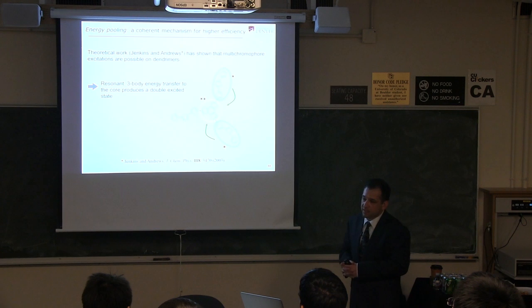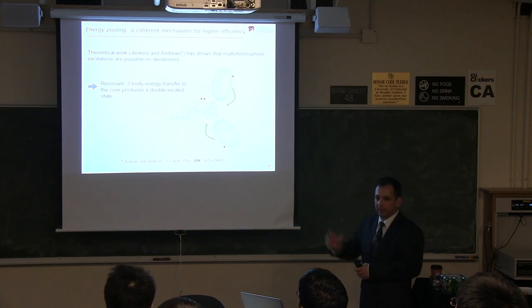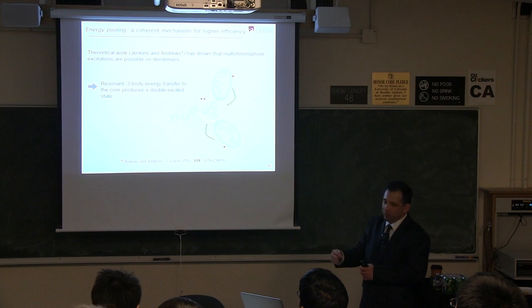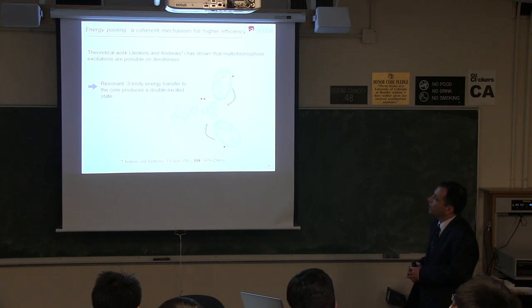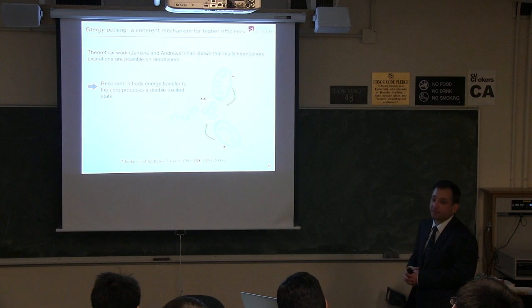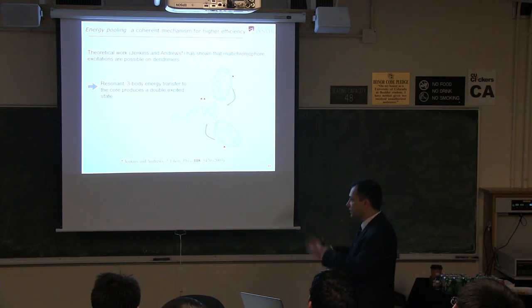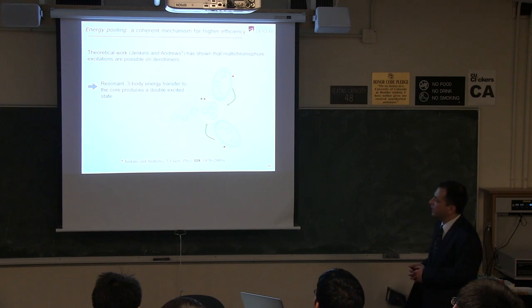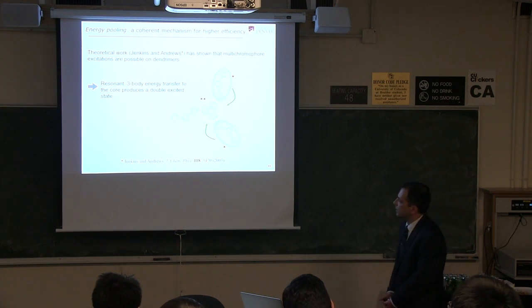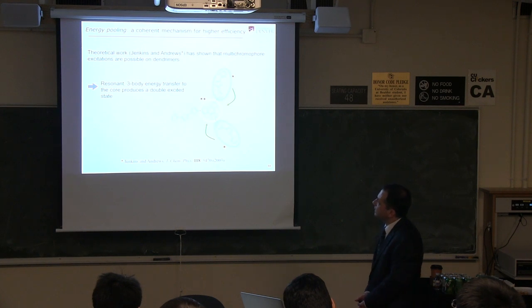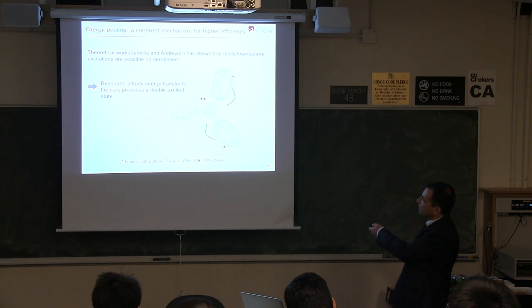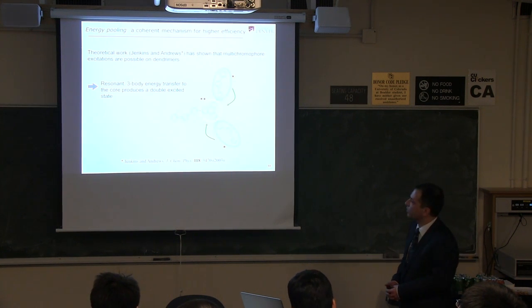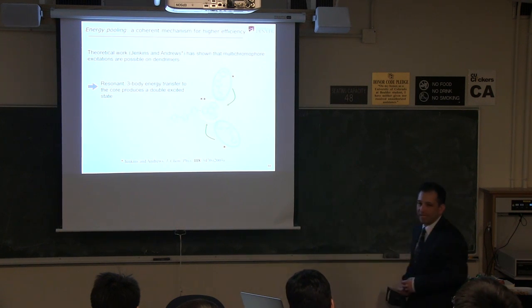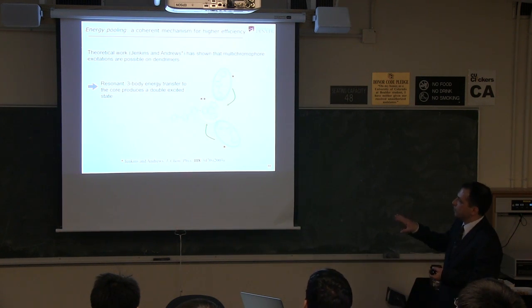Now, in natural photosynthesis, that happens with one excitation at a time. One chromophore absorbs a photon, funnels it to the reaction center, you get a chemical reaction. We'd like to do that twice at the same time. And the theory behind this was more or less worked out about 10 years ago by David Jenkins and David Andrews at University of East Anglia. And this is called energy pooling, where you've got two excitons on the arms of the material that can pool simultaneously through a quantum coherent process into the center. And this would give you a doubly excited state. So before I talked about the S1 state, these are S1 states, this becomes an S2 state.